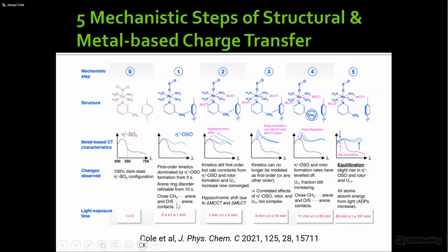And there are some close contacts. That's what we expect from this ring rotation to alleviate the steric strain. So all of that is fairly modelable, first order kinetics up to about 10 seconds. Then it gets a little bit more complicated. It's still first order, but the rate constants have sort of converged, in terms of the rotor formation, the oxygen-bound sulfur dioxide, and also the U11, that's of the methyl group, have increased.